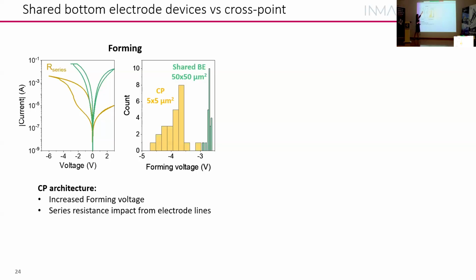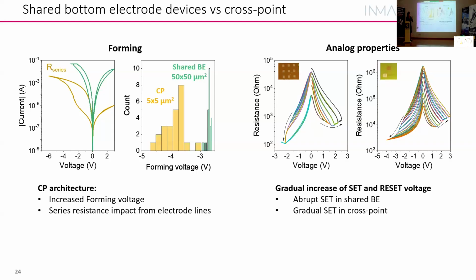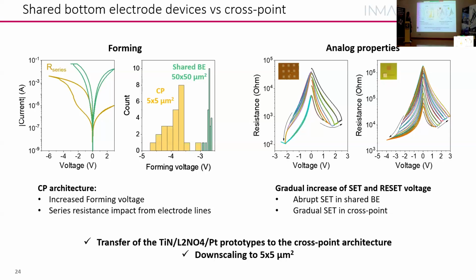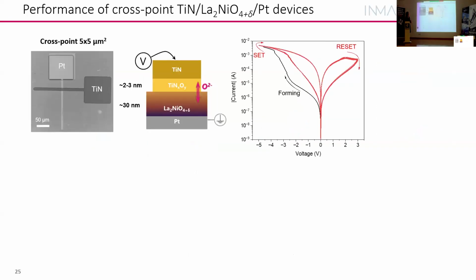So we saw these are the ones in yellow are our new crosspoint devices, we saw that we had to apply a higher forming voltage to make these devices work, and that there was a series resistance that had an impact in the switching curves. However, we had very nice analog properties. So we had a more gradual reset in the crosspoints devices compared to the other devices. And finally, we can say that we successfully downscaled to 5 by 5 micrometers. So we reduced and we could operate them very nicely.